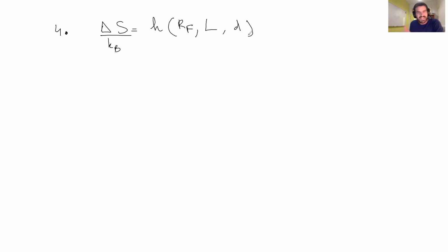However, forces, external forces, not entropic forces, forces like F, the operator's force, the work, are not included in the entropic description. It's more an enthalpic or energetic aspect. So we can be sure that there should not be any effect of the force here. Of course, the force will elongate the chain, and since it's elongated, then you have a certain size. So this will play a role in the configurations. But the force itself cannot appear in the entropy. It's a different concept, as you all agree, I guess.